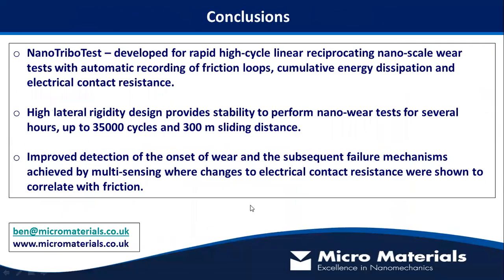So hopefully I've given you a flavor of some of the potential of this nano tribo test system, which we developed for rapid high cycle linear reciprocating wear testing. So we've enabled it to have automatic recording of the friction loops and the cumulative energy dissipation, and combining those with electrical contact resistance. And this multi-sensing approach is particularly useful to improve our understanding of the onset of wear and the subsequent evolution of the failure behavior. So the instrumentation design retains the high lateral rigidity in the load head, which provides the stability to perform these tests for several hours. And we've gone right up to, as I say, 35,000 cycles, and even 300 meters of sliding distance, which is an extremely large sliding distance for a nanoscale test.